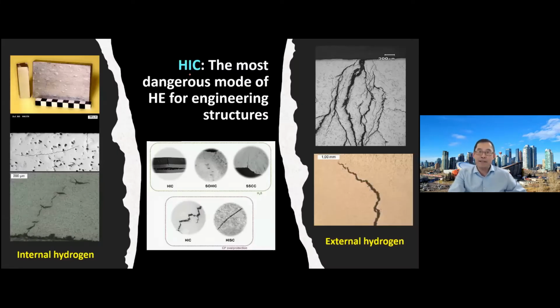Hydrogen-induced cracking is the most dangerous mode of hydrogen embrittlement for engineering structures. The cracks can form internally and from the metal surface, depending on where the hydrogen is located and how it reaches the cracking condition. At the same time, it depends on the environment: H2S is available, or hydrogen is introduced by over cathodic protection. We can also see different features of the cracks in terms of orientation of the stress or different phenomena of crack growth. You can see lots of different terms describing hydrogen-induced cracking. But the common thing is the crack is caused by hydrogen, of course combined with other conditions I will talk about later.